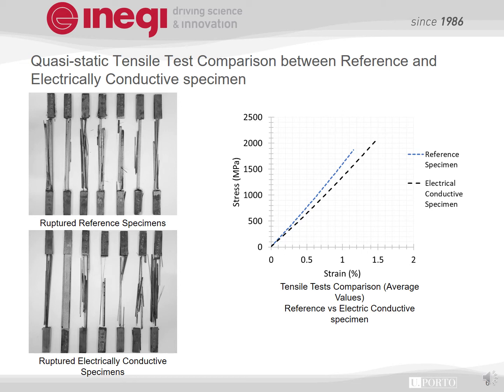Figure on the left hand side shows the ruptured specimen at the end of the test after reaching the maximum strength. Specimens did not fail in the middle, but the fiber seems to be separated in the direction of the orientation of the ply. Each fiber bonded with the matrix seems to get separated after reaching the maximum tensile strength. Both reference and electrically conductive seem to have the same failure behavior.